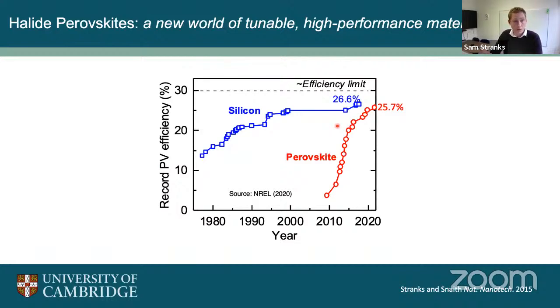And it's likely that they'll approach the value of silicon, perhaps even later this year, which is a really exciting time. And one of the reasons they're particularly exciting from a scientific point of view is that we can process them very crudely and at low temperature. If you remember, I told you how for silicon cells we have to heat them to very high temperatures to get rid of defects. With these perovskites, they seem to be very tolerant of defects. We don't have to heat them very high.